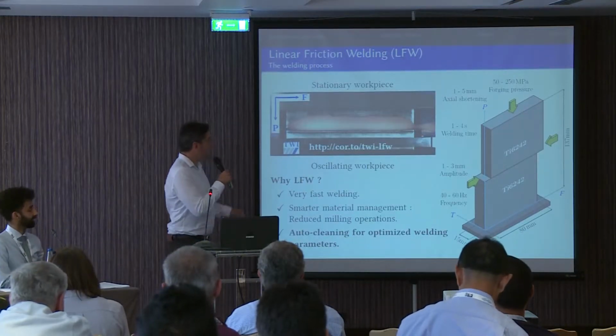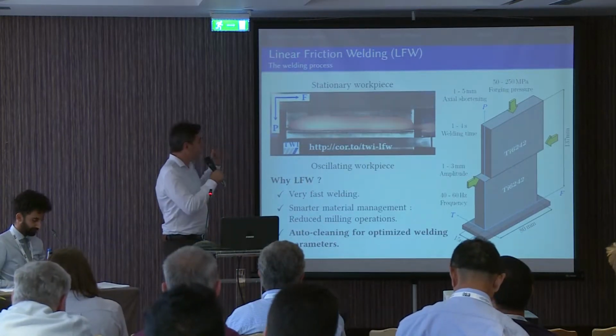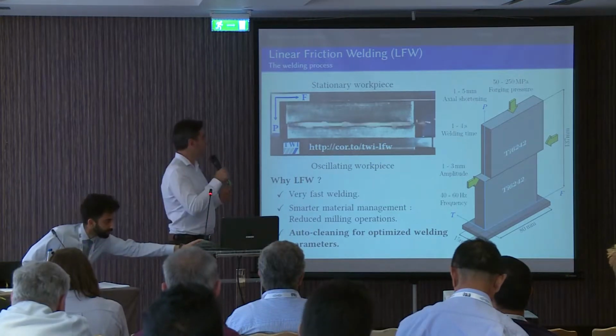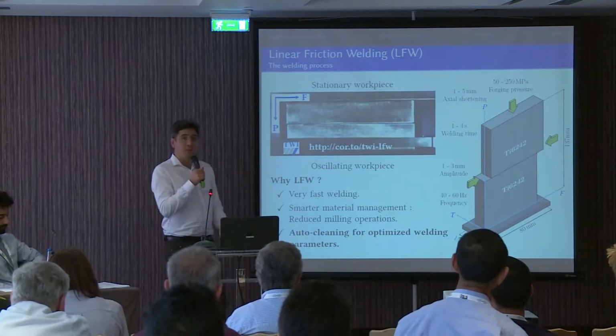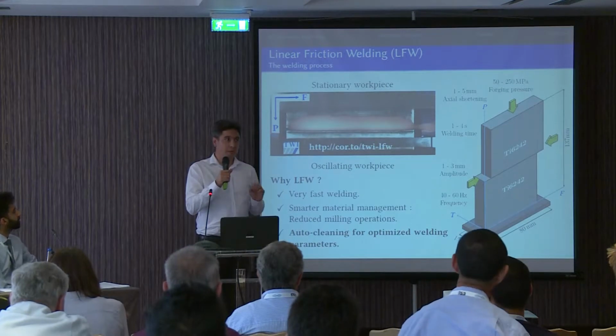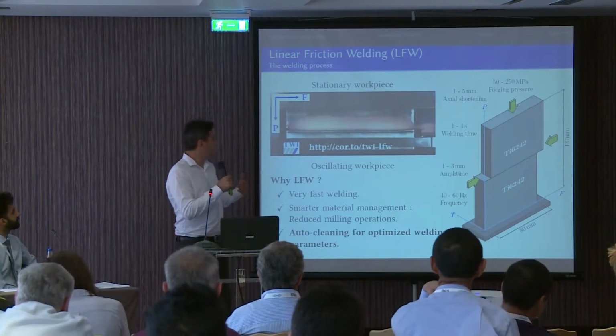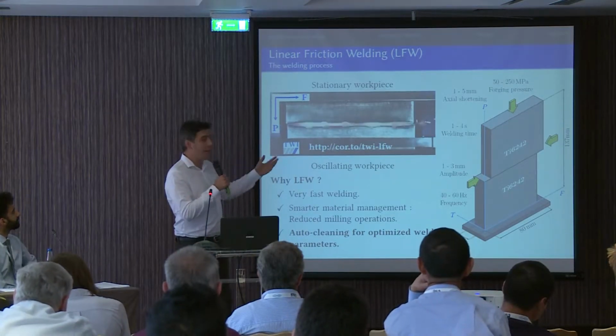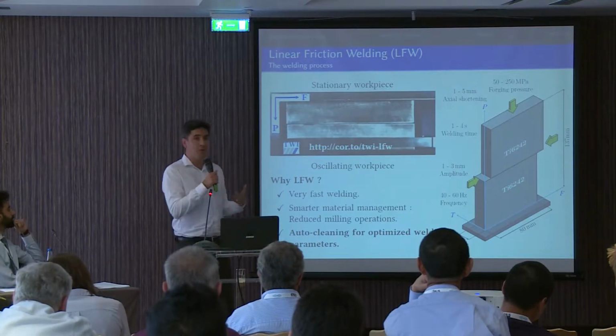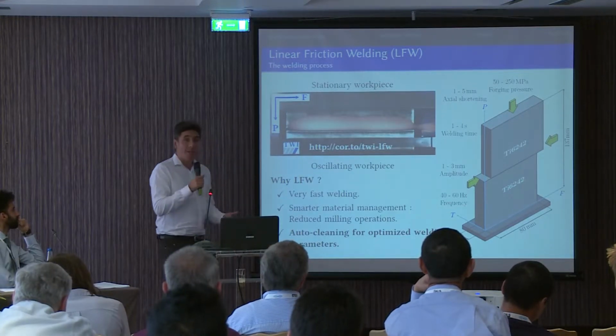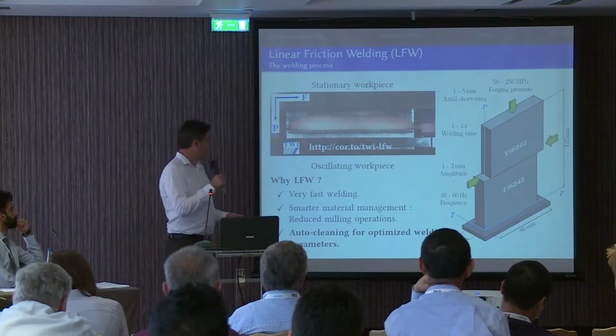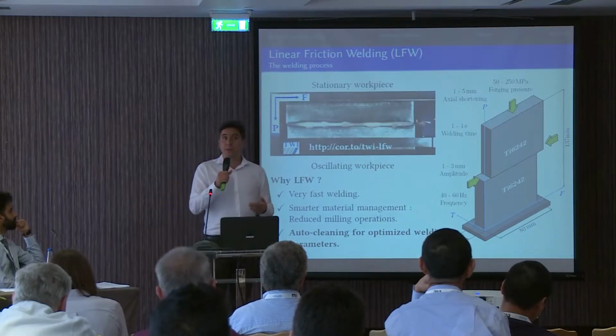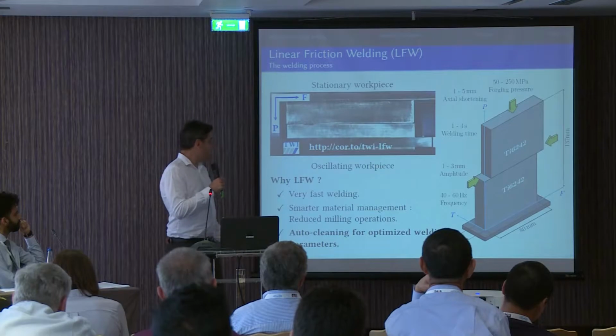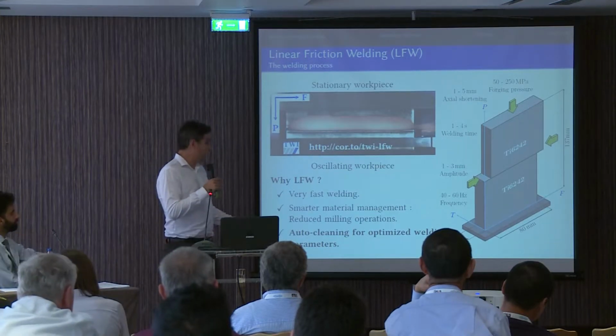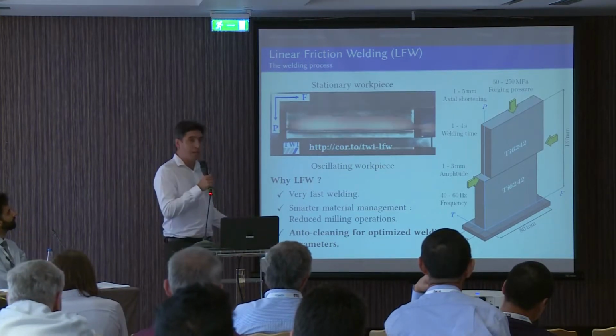So we have two work pieces. One is fixed, and the other is describing an oscillatory motion. And after a second, we are going to apply enough pressure force in order to get the sound weld. Why is it interesting? Well, it's a very fast welding. We can perform dissimilar welds, and for optimized welding parameters, we can get an auto-cleaning process.